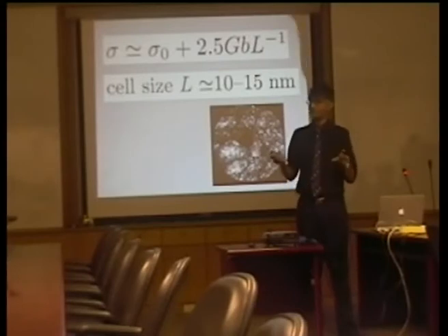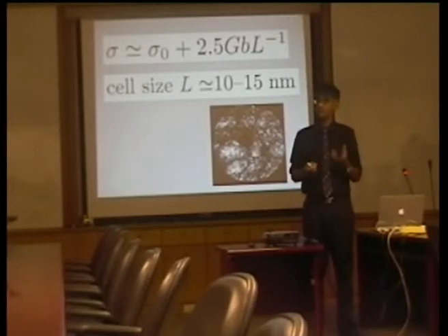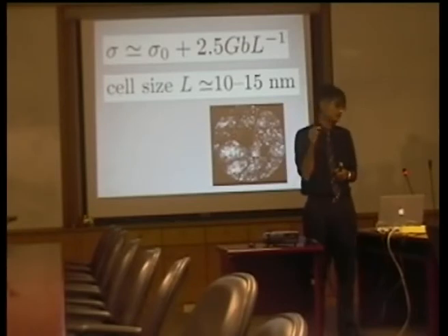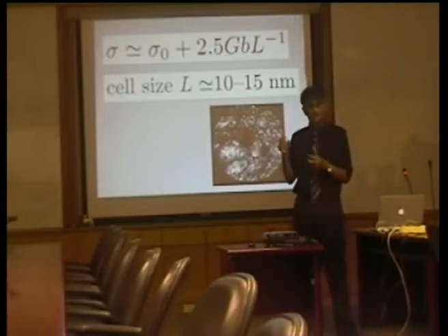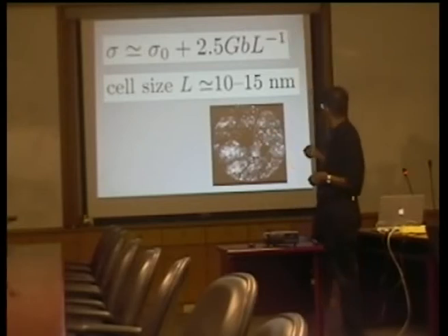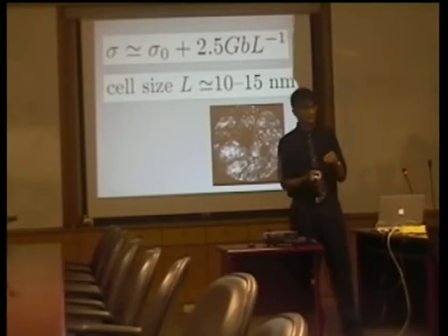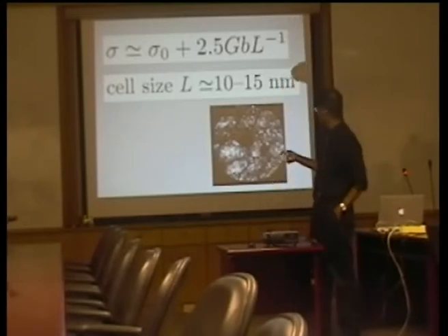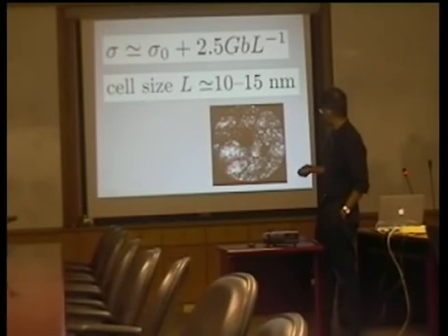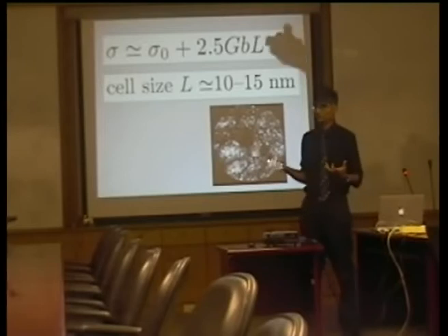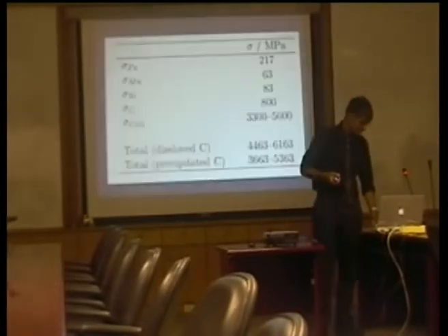Now, you're all probably thinking this is wrong, because we know that the Hall-Petch equation says that the strength should vary with d to the minus a half. But when we get to this small a grain size, that equation doesn't apply, and it should vary with 1 upon the grain size. So when we get to a very small grain size, the strength increases very sharply. If we do a calculation of strength according to the grain size we have measured here, which is 10 to 15 nanometers, then we get a huge contribution to the total strength from the grain size itself.